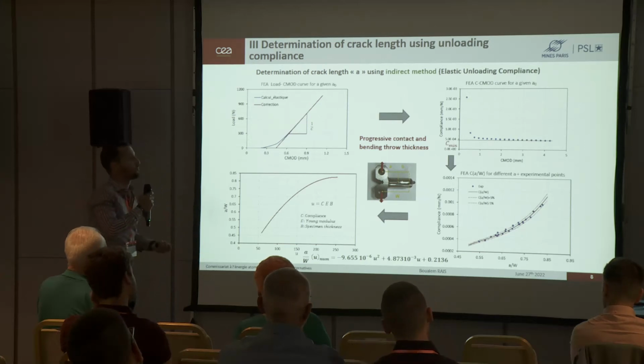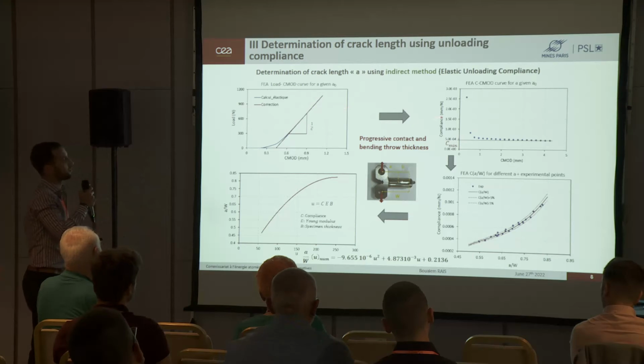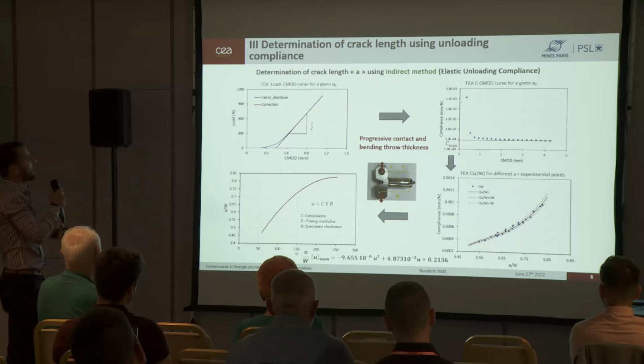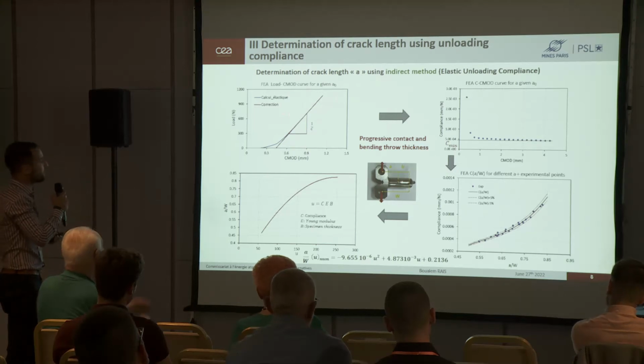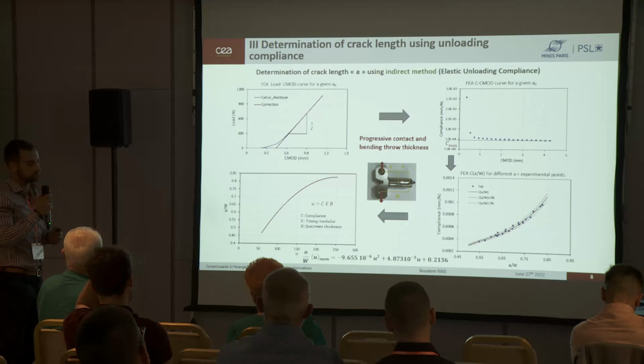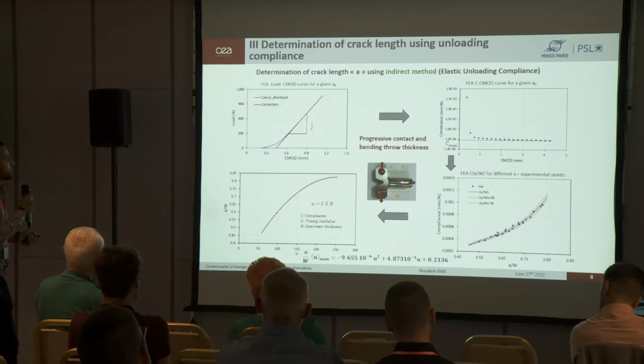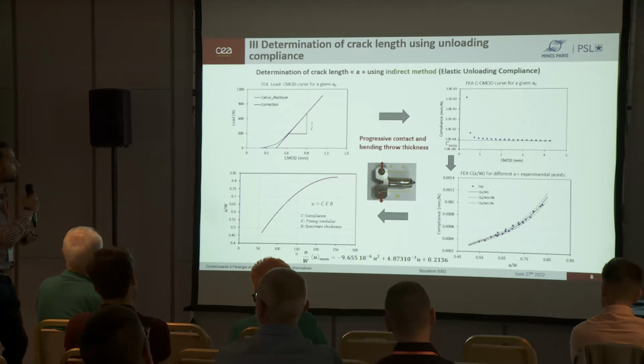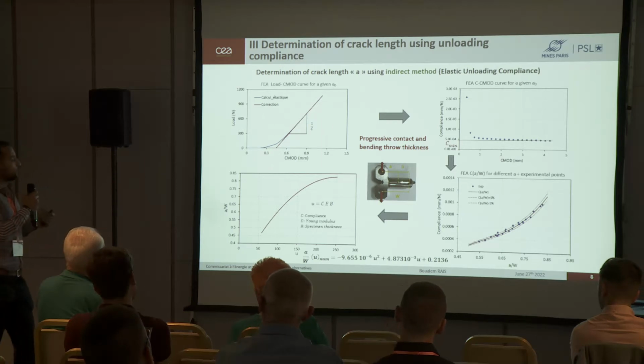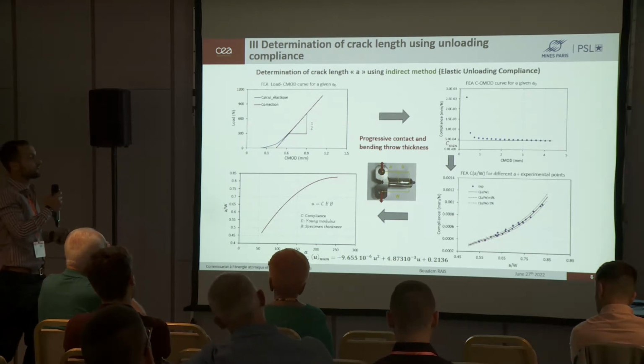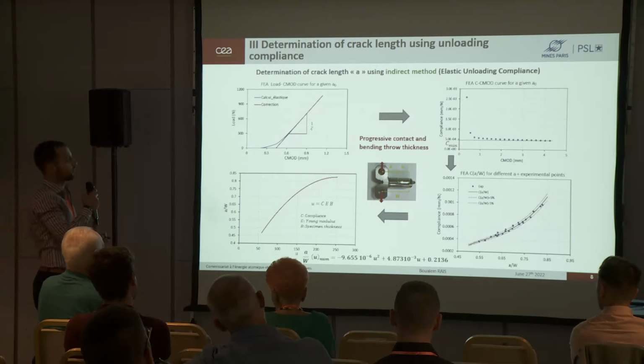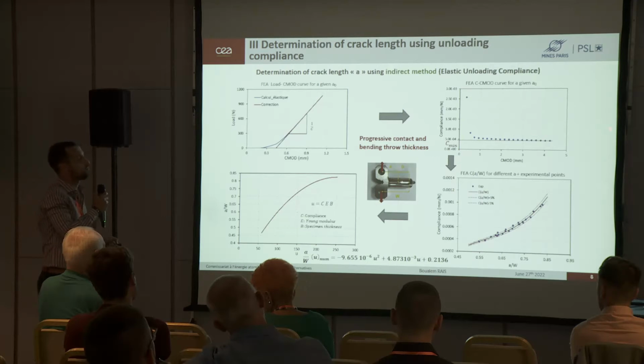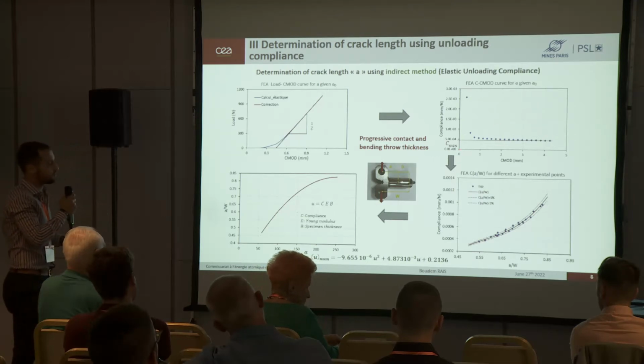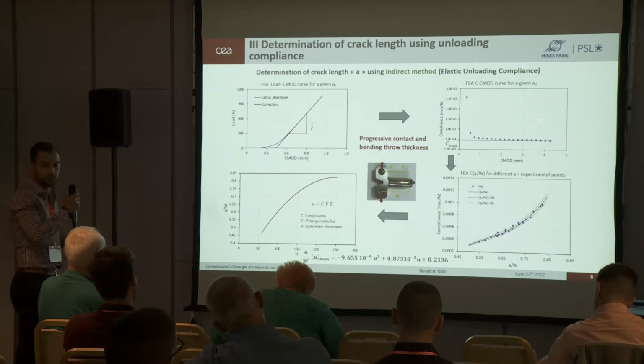Now, let's talk about the determination of the crack length. During some elastic finite element calculations, for a given crack length, we highlighted some phenomena that weren't known before. These phenomena are the inflection of the curve at the beginning of the loading before being linear. The phenomena responsible for this inflection are progressive contact and bending through the thickness. The effect of these phenomena is the decrease of the compliance before reaching a minimum value, and it is this minimum value that we attribute to every crack length that we simulate.